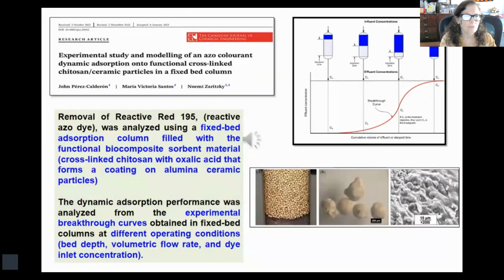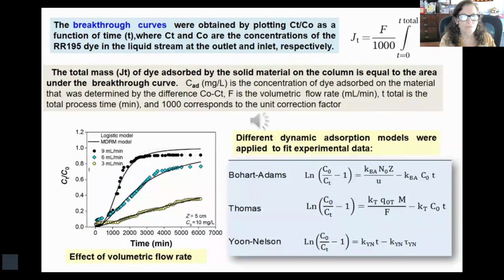Finally, the removal of the azo colorant was studied in fixed bed columns filled with the ceramic particles coated with cross-linked chitosan oxalic acid. The dynamic adsorption performance was analyzed from the experimental breakthrough curves at different operating conditions: bed depth, volumetric flow rate, and dye inlet concentration. The breakthrough curves were obtained by plotting dimensionless concentration as a function of time. Different dynamic adsorption models were applied to fit experimental data: Bohart-Adams, Thomas, and Yoon-Nelson.